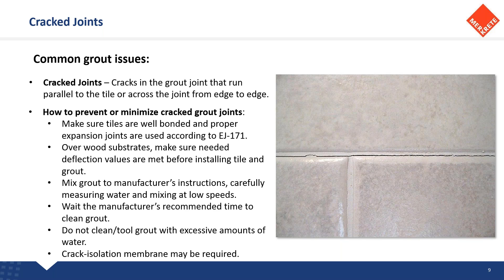Some people do a two-wash system; I've always done a single wash system where I slurry, tool my joints, wipe it clean, and don't touch it again until I come back to buff off any residue or haze. We want to introduce as little water to these products as possible while cleaning. Crack isolation may also be required — we manufacture crack isolation membranes and truly believe in them. That insurance can prevent tile or grout from cracking if there's any in-plane movement less than an eighth of an inch.